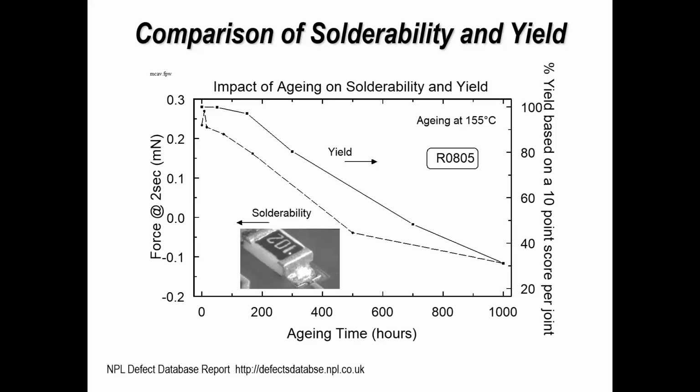What I show you here is a slide taken out of one of our NPL presentations from a few years back with Dr. Chris Hunt. It shows measurements of components after natural aging and also after forced aging. We can see that the graph is going down from left to right, and this indicates the impact on results of the baking process. And these are direct measurements. However, not everybody has a wetting balance and is able to measure solderability wetting forces.